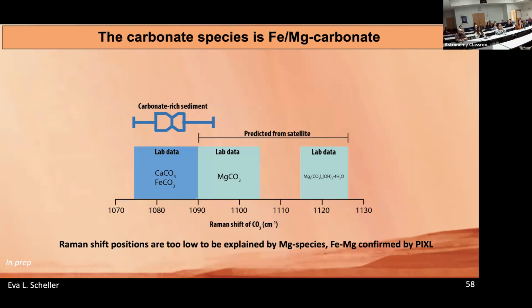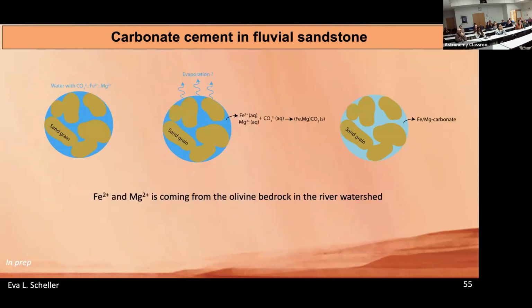Again, looking at the Raman positions of the carbonate, we observed that these are not magnesium carbonates, but mixtures of iron and magnesium carbonates that are typical of, again, olivine dissolution with these mixed cation environments. So how can you get carbonate in a sandstone? There are a few ways, but this is the most typical process for how to do that.